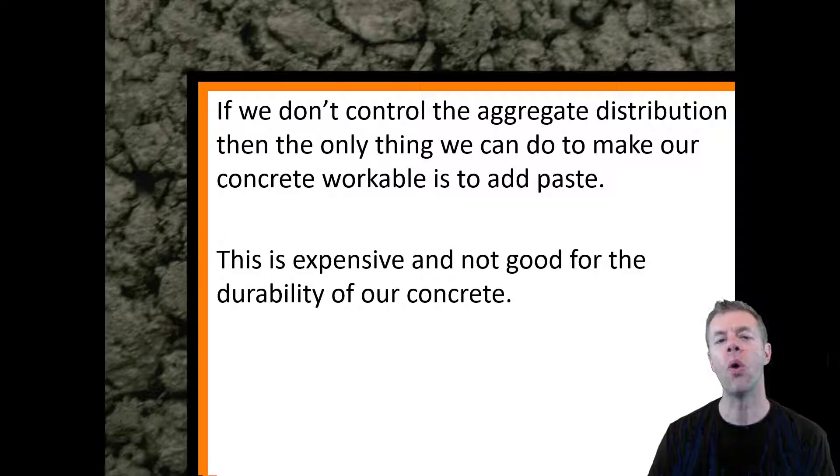If we don't control the distribution of our aggregates, then the only thing that we can do to help make our concrete more workable is to add paste. That's cement and water. That's all we can do. And if that's the only thing we can do, if we run into one of these unfortunate gradations, if we just increase the paste content, it's not good for the durability or the cost of our concrete.